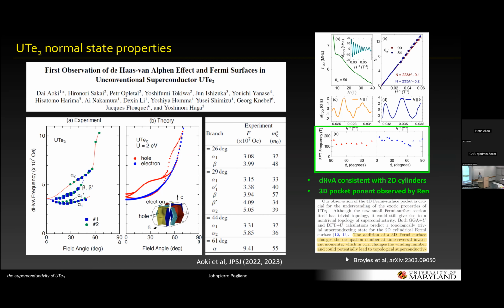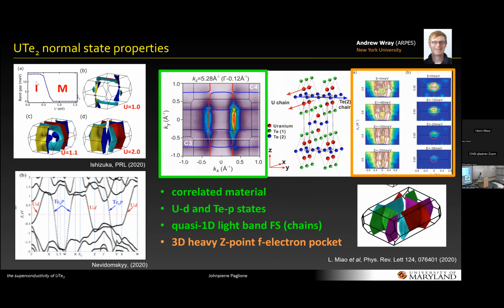So what you referred to as theory, with U equal to 2, is that a DFT calculation? This here, yeah. But the usual strength of the U's that we look at is not so strongly correlated, right? Okay, so you get these uranium D and P states to cross and give you this band structure with some U. There's no F states in this band structure. So this is D, D, U, right? Yes, but there's no F states coming up, at least in DFT calculations. Correct.